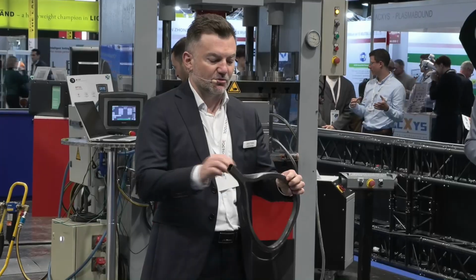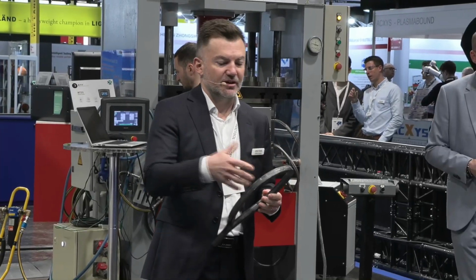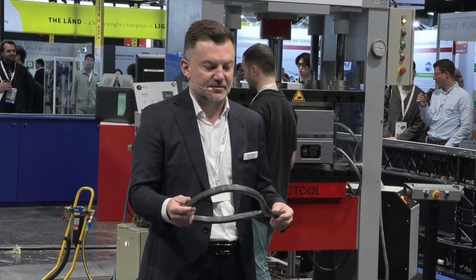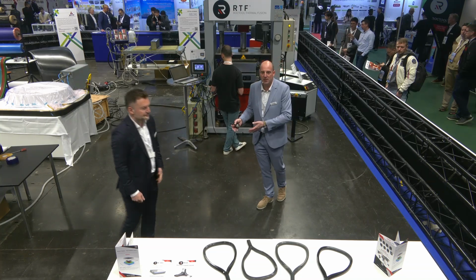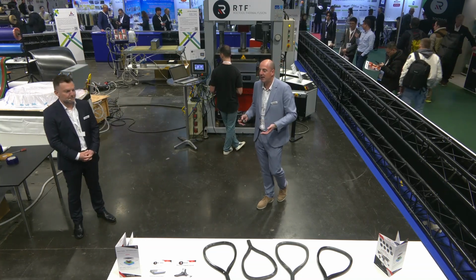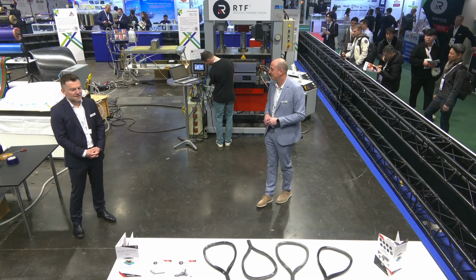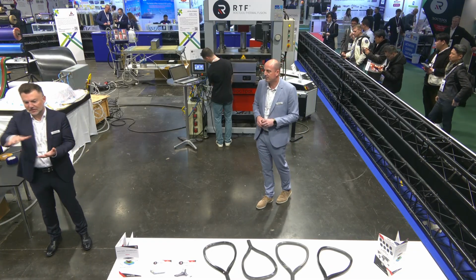What's interesting is we also get a resin-rich surface. We can see the polycarbonate that is flowing well on the UD, which then allows the manufacturer to do a decoration step and be able to decorate the piece. We can also add that in this configuration and demonstration, we use carbon, but the whole system can be used with many different materials, from glass fibers, carbon fibers, of course, and also natural fibers. So you can adjust as you want, depending on the processing and the material in link with your application. You keep the same equipment, and you just have to manage different temperatures in link with your material.